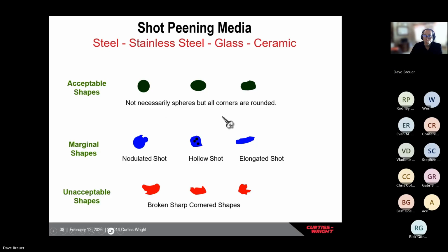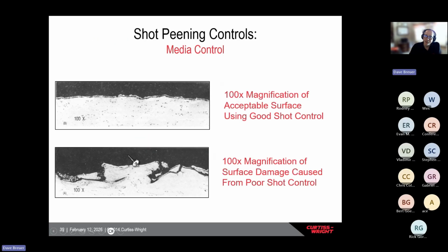Whenever you do controlled shot peening, you want all of your media's external surfaces to be essentially round. You do not want surfaces with sharp corners, because if you're throwing this media at high velocity, those sharp corners can put stress concentrations into your parts. This is an exaggerated example, but it's at 100x magnification.